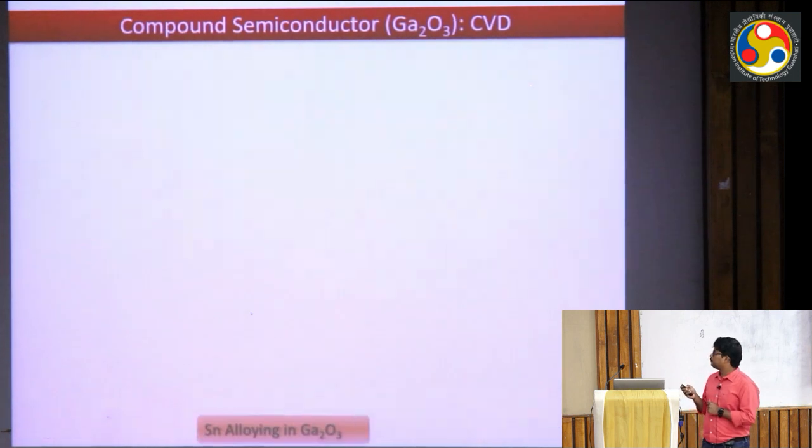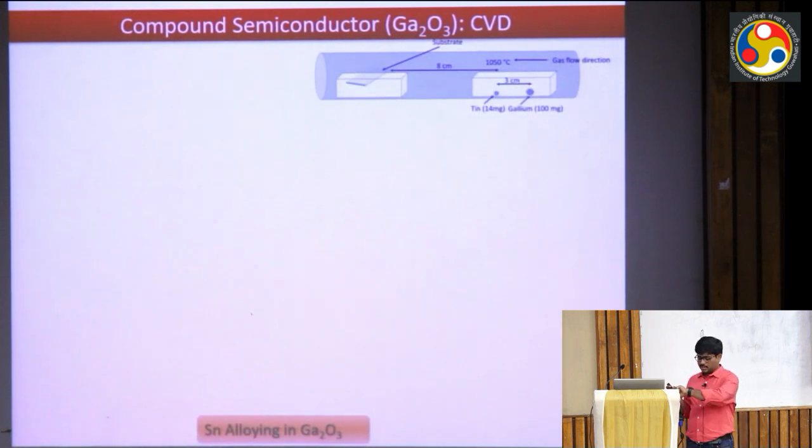So how can precursor control lead to different morphologies for growing a semiconductor? Then another thing was how to dope this material. As I just mentioned, gallium oxide has a very wide band gap, and typically an insulator also has a very wide band gap. So don't you think, how can you use gallium oxide as a semiconducting material? Yes. I think 15 years back or so, people used this wide band gap semiconductor as an insulator. But very recently, they could dope this semiconductor. Again, this is irrespective of gallium oxide or any other semiconductor.